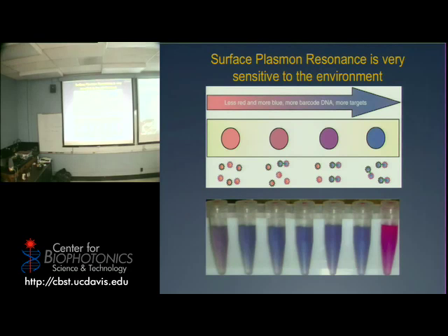And what happens is that when you increase the ionic strength of the solvent, they're stabilized electrostatically, remember? So these guys are negatively charged. The only reason why they're separated is because if they get too close, there's this big repulsion coming from these 2 negatively charged. But if you increase the ionic strength by adding salt, you shield this repulsion. So they have a tendency to aggregate, right?